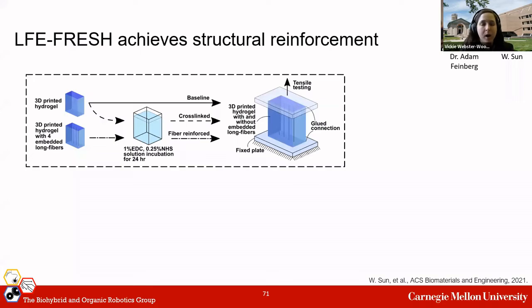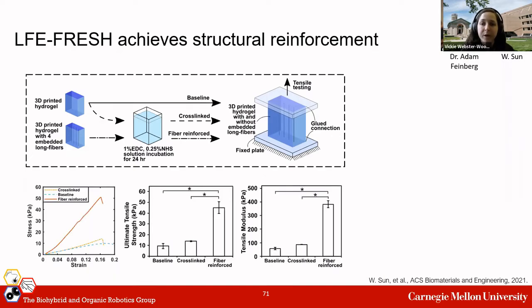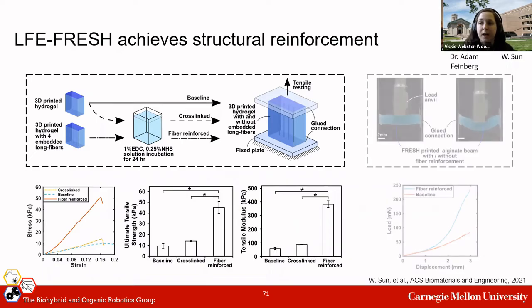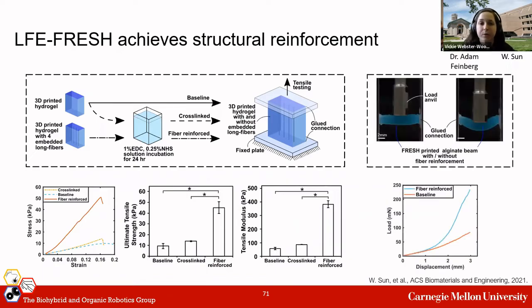Furthermore, one of the primary benefits that we anticipated with LFE FRESH was the ability to structurally reinforce these printed hydrogels. To test this reinforcement, we performed tensile testing with and without fiber reinforcement. And we found that, as expected, LFE FRESH printing significantly increased the ultimate tensile strength of our composites. As one would expect, this reinforcement also improves composite strength in bending.